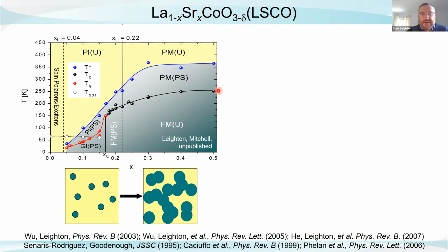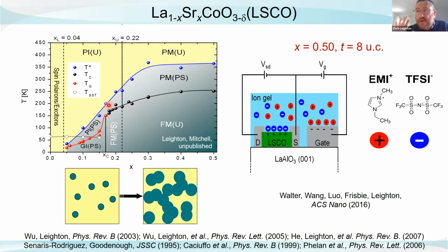The Curie temperature at x equals 0.5 is about 250 K. It goes all the way up to above room temperature at x equals 1. So what drew us to this was the possibility that we might be able to sit just underneath a percolation threshold and then gate across it with an electric field and get an anomalously large increase in Curie temperature, saturation magnetization, and so on. Okay, so I will show you that towards the end of the talk. To start with, I'm going to start somewhere simpler. We're going to be working here at x equals 0.5, where the system's a uniform ferromagnetic metal.